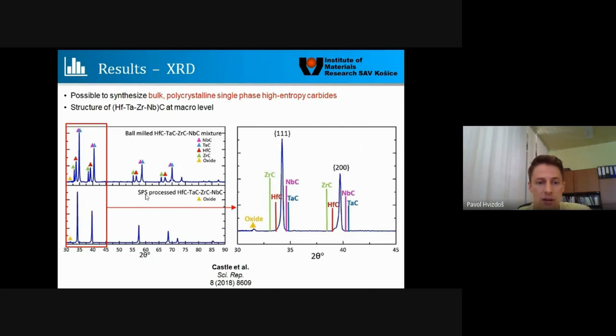After SPS, so after sintering, you can see that the peaks disappeared, which confirms that a single phase bulk material was formed. In that graph, you can see a slight peak which corresponds to an oxide peak, but this is just because this graph is a relatively old graph, and this was one of the first trials. Since that time, we prepared other types of high entropy carbides, which were completely single phase without any remaining oxides.